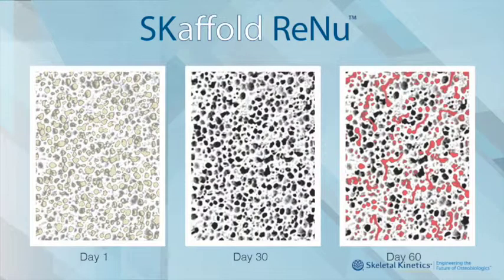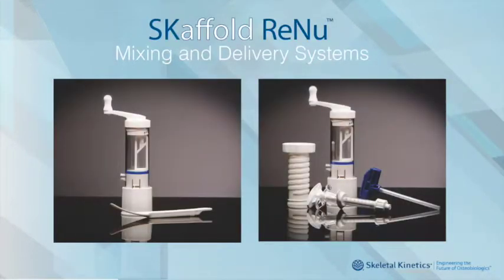In this series of images, we see examples of the remodeling and resorption process. At day 1, a cured hydroxyapatite matrix is exhibited. At day 30, we see that the sulfate has mostly resorbed, leaving a very macroporous vascular graft. And at day 60, we see that bone infiltration and remodeling has already occurred, and the graft is remodeling inside out and also outside in. Let's learn now how Renu works.